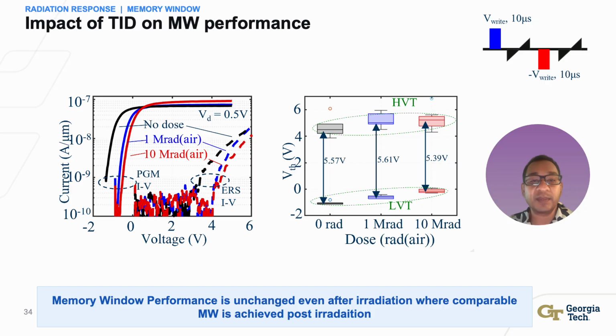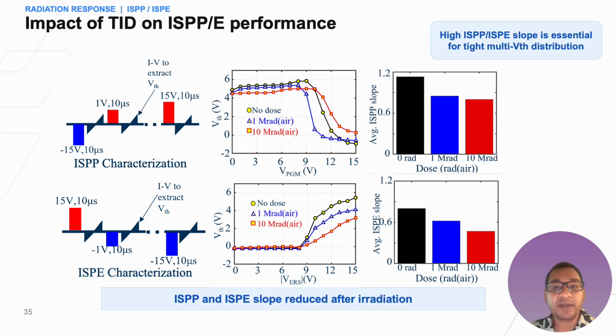Importantly, this experiment measured post-irradiation programmability. It is different from asking whether the data written before the irradiation remains unchanged. A large final memory window does not mean that the programming dynamics are unchanged. We use incremental step pulse programming and erase, or ISPP and ISPE. Instead of applying one large pulse, the pulse amplitude is increased in 1 volt steps and the threshold voltage is measured after each step.